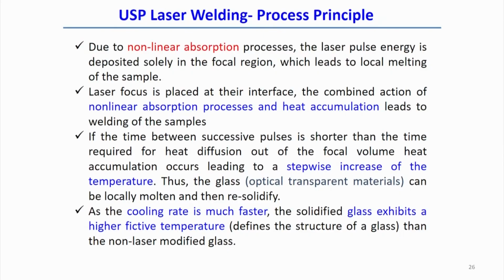In the processing principle of the ultrashort pulse laser, a nonlinear absorption process is observed, and the laser pulse energy is deposited only within the focal region, which leads to very localized melting of the sample. Another advantage is that the heat affected zone on the surface is very small, which is not comparable to conventional laser welding processes. The laser focus is placed at the interface, and the combined action of the nonlinear absorption process and heat accumulation leads to the welding of the sample. That is why this process is mostly applicable to glass. If the time between successive pulses is shorter than the time required for heat diffusion, which happens in ultrashort pulse laser application, there is a stepwise increase of the temperature.